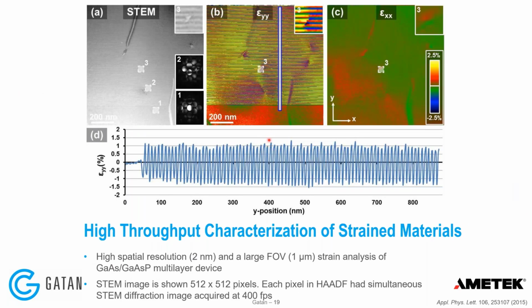I like this example because this is one of the first publications out there using K2 IS, actually, a long time ago, and the STEMx to collect 4D STEM data set and do nanobeam diffraction strain mapping. As you can see, the high speed of the camera, they were running the camera at 400 frames per second, which is relatively slow if you think about today's standards and how fast we can go with cameras today. But this was quite fast at the time. They were able to record a 4D STEM dataset from a quite large field of view and then calculate the strain, and as you can see, get this nice statistical information throughout many layers in the sample here.